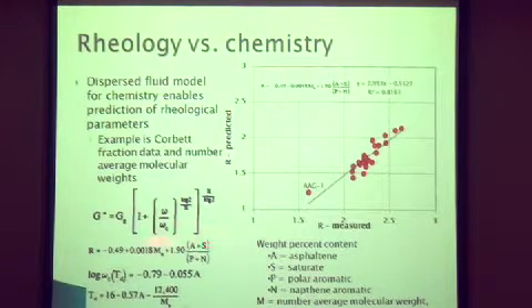You can see here the equation for the shape of the master curve. Here I have my asphaltenes, saturates, polar, and my naphthenic aromatics. Then I have my molecular R value. Calculate all the other parameters using different equations. We can link the chemistry and the rheology very nicely together.